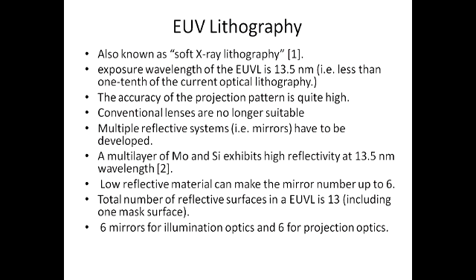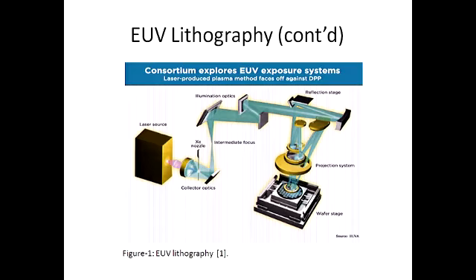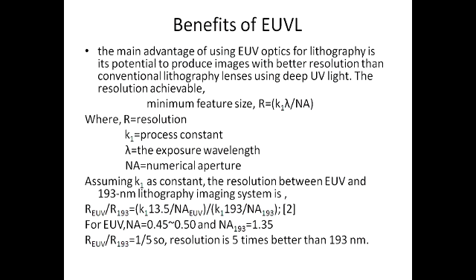And of course, the accuracy of projection pattern is very high in EUV lithography. This is basically the exposure system, but I will not go into details. This is just how it looks. EUV also deals with Rayleigh's equation, and we know the minimum feature provided by Lord Rayleigh, and the equation is R equals k1 lambda by NA. We define k1 as a process constant, lambda as the exposure wavelength, and NA as the numerical aperture. If we compare EUV with the 193 nanometer lithography technique, what do we find? At the bottom you can see there is a ratio between the EUV minimum feature over the 193 nanometer minimum feature.